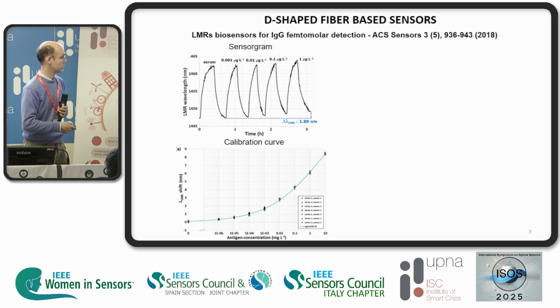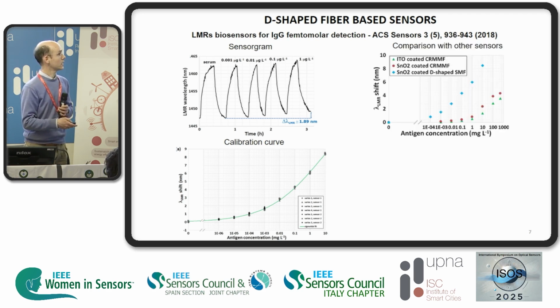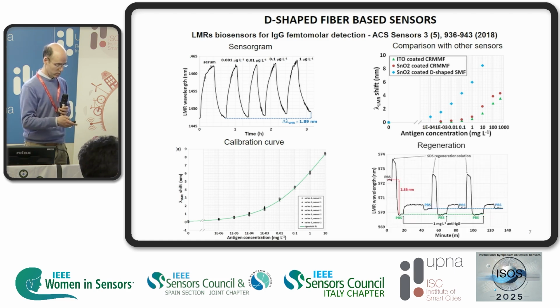This is the calibration curve obtained with 4 different sensors. This is the sensorgram, where we can see the wavelength shift in serum. And here is what I was saying before. If we compare D-shaped fiber single mode with cladding removed structures, which are multi-mode, the wavelength shift in the biosensor is much higher than in the other case. So this work is probably the only one or one of the few works where we compare single mode structure with multi-mode structures. And regeneration. The sensor could be regenerated several times under the same concentration in SDS solution.